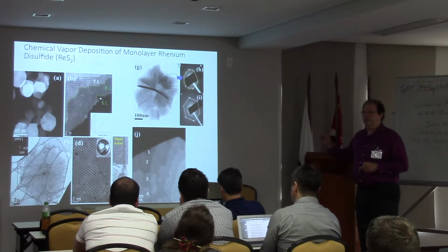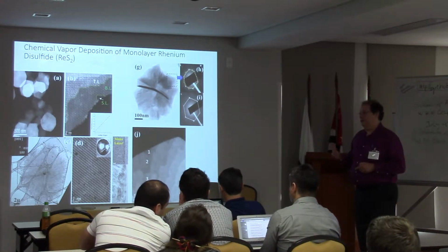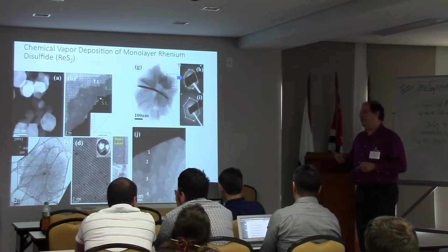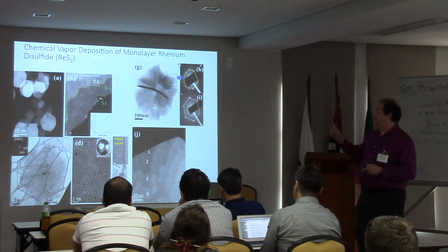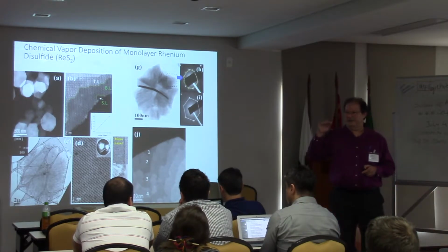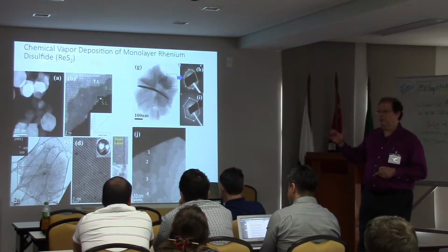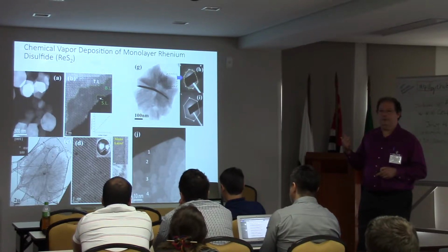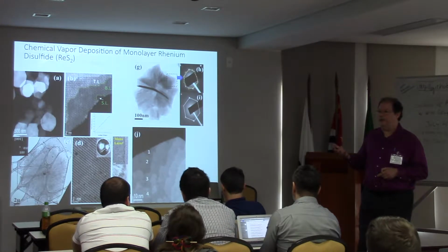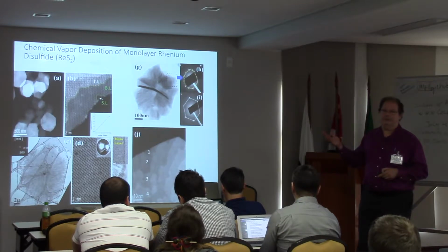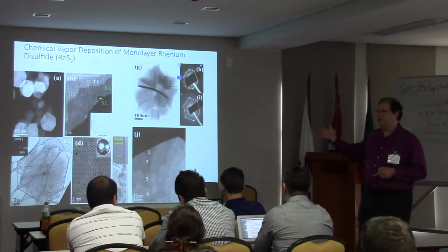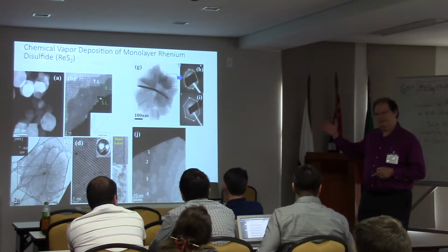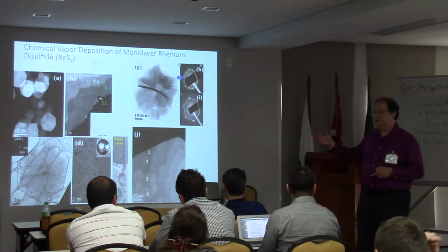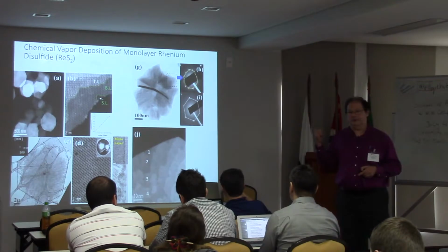If you want to dope a material, there are in general very few ways to do this. You can do it by doping, you can do it by chemical functionalization. In this case, that's very clever. Instead of using this approach, what's the price to pay? We start losing some of the good qualities, the electronic properties of the material. For instance, if you functionalize graphene very much, you lose the high velocity of the electrons. If I start to functionalize very, very much, we start destroying some of the electronic properties. You're losing mobility. That is very important for transistors.